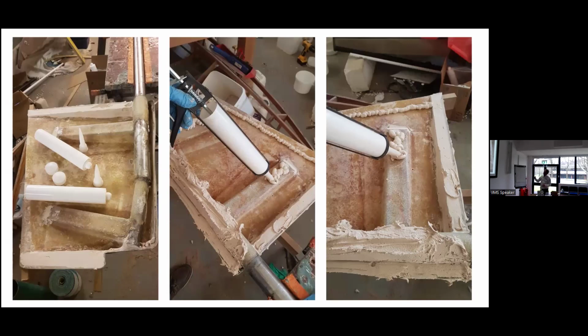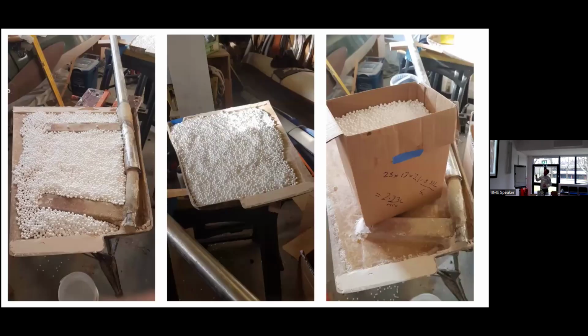So on the next slide, what I did there was that you can see this calculation, just like a rough cardboard box calculation. The foam expands 4 times its original volume. So I calculated the volume required with some beanbag beads, and then I reversed the mathematics, the litreage of the epoxy I needed, and then calculated the weight I needed. So I could actually get down to exactly 2.23 litres mix would yield 8.95 litres, which I measured off on that cardboard box of expanded foam. And so the next slide, you see the whole lot.